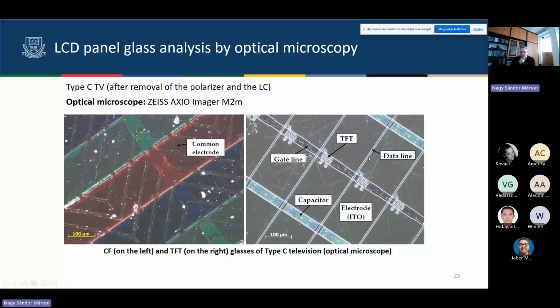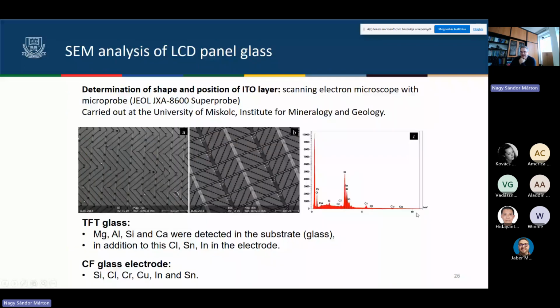Here are some optical microscopic pictures of the CF glass, the color filter glass, and the TFT glass. Actually, the indium tin oxide layer cannot be seen in these pictures because it's optical microscopy, and this layer is transparent. But here in the scanning electron microscopy, this gray material is the surface layer, which is made from indium tin oxide and responsible for the voltage and the transparency.